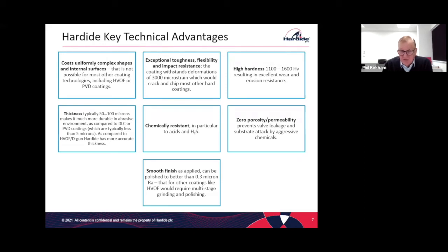Chemically very resistant because there's no porosity in the coating, so fluids can't get through. On valves particularly, it prevents leakage because the coating stays intact. The hardness of the coating, 1,100 to 1,600, was chosen because it's harder than quartz sand. So sand is a ubiquitous pollutant, something that's found in many areas, and the sand will not scratch the coating.